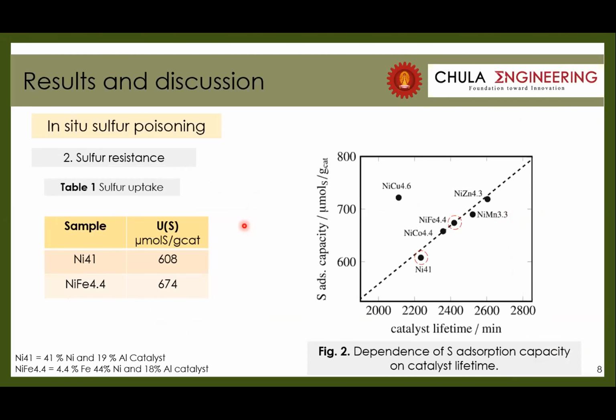Then one is sulfur resistant. Table 1 shows the sulfur uptake of the iron-promoted catalyst is higher than the unpromoted catalyst, and Figure 2 confirms that hydrogen sulfide not only absorbs on the nickel catalyst but also on the iron promoter. In other words, the iron promoter can protect the nickel metal from sulfur,